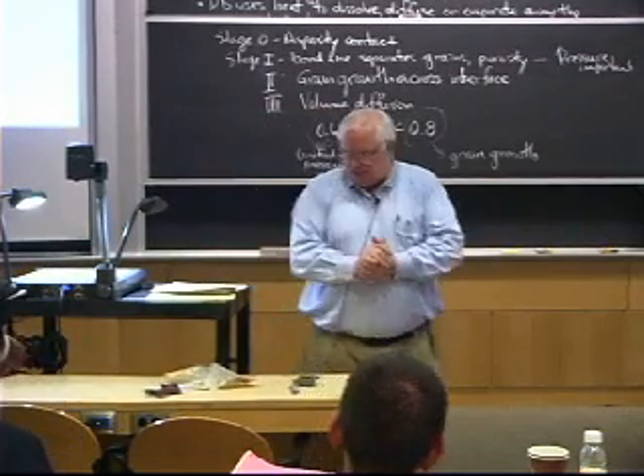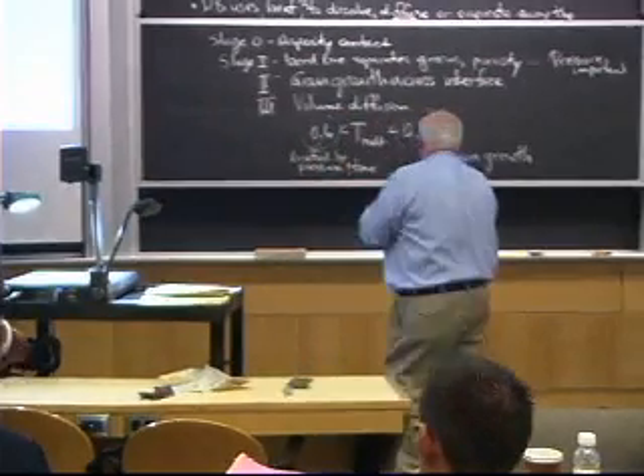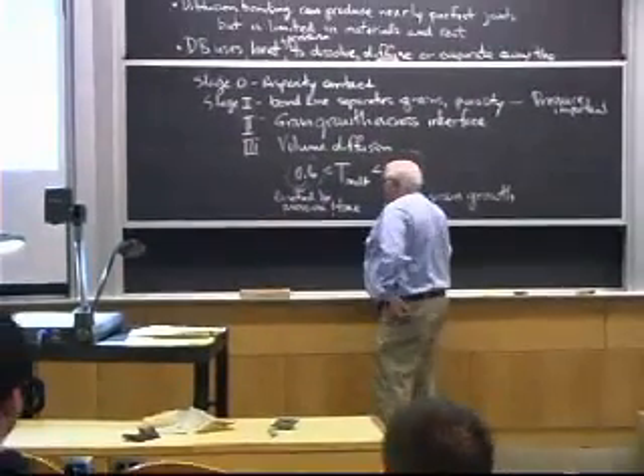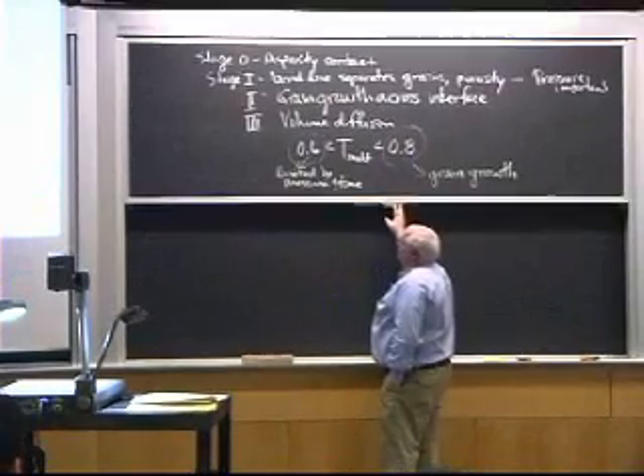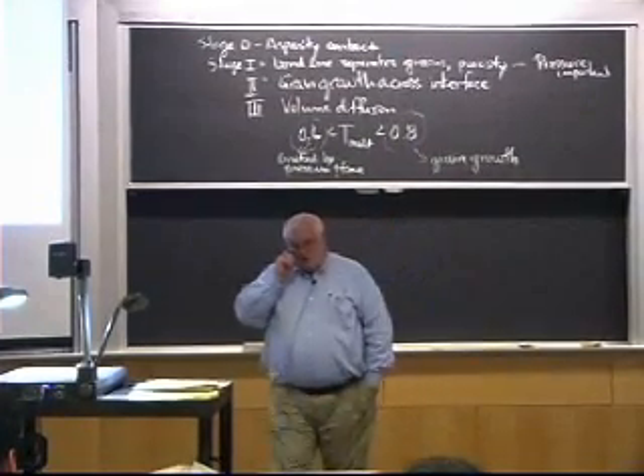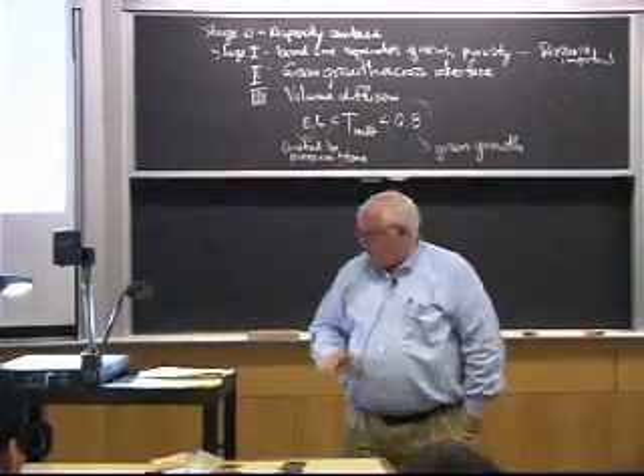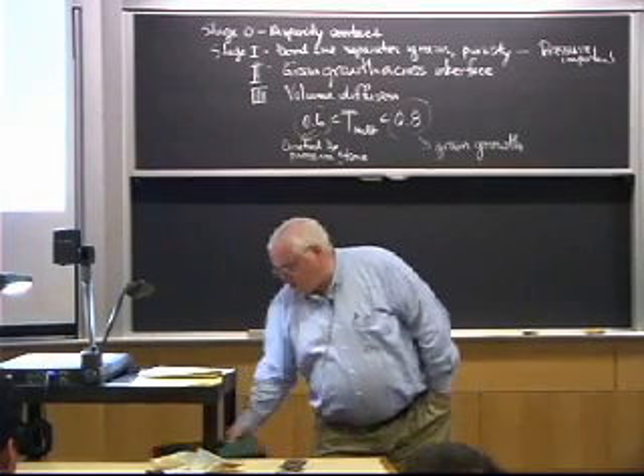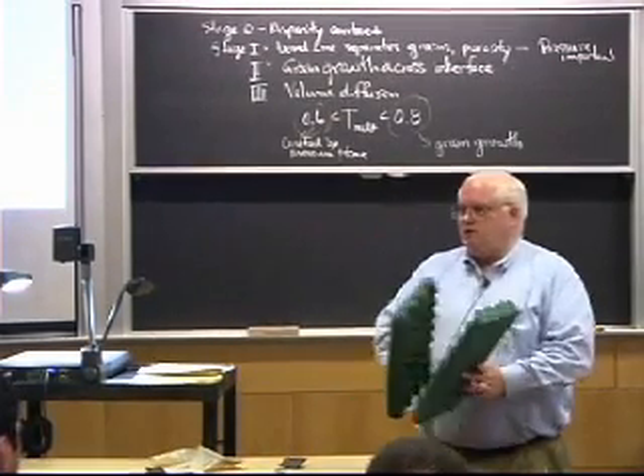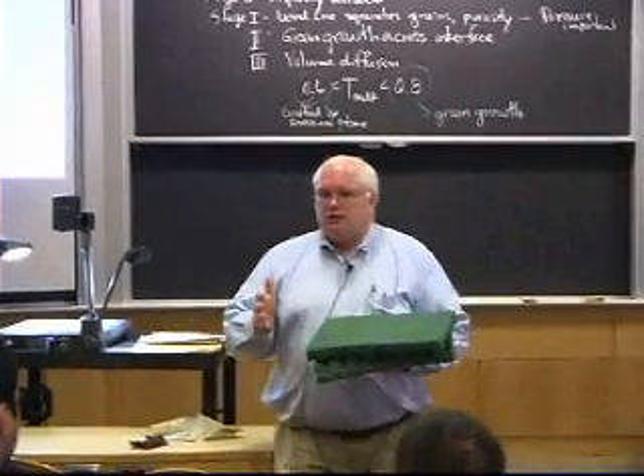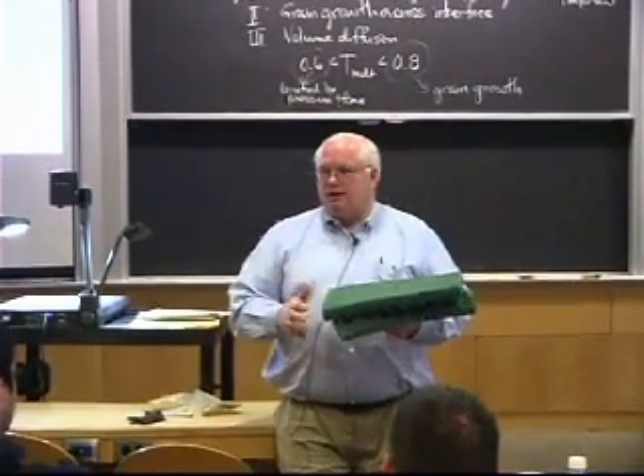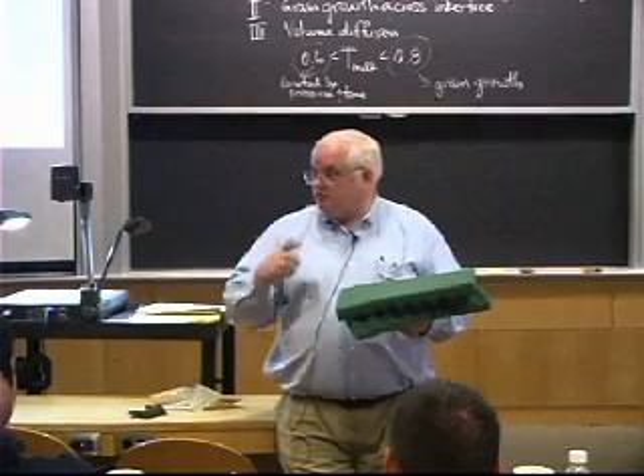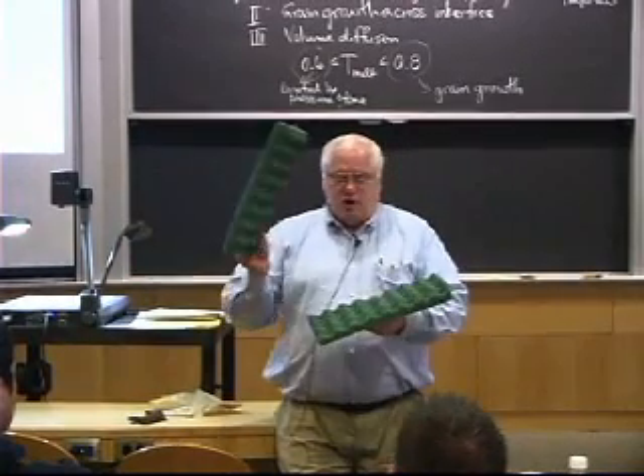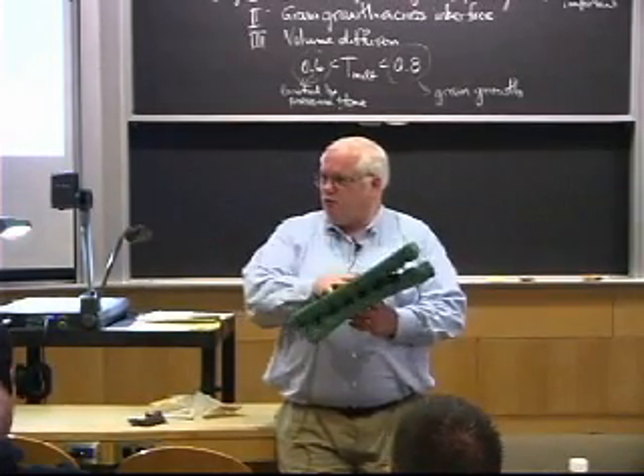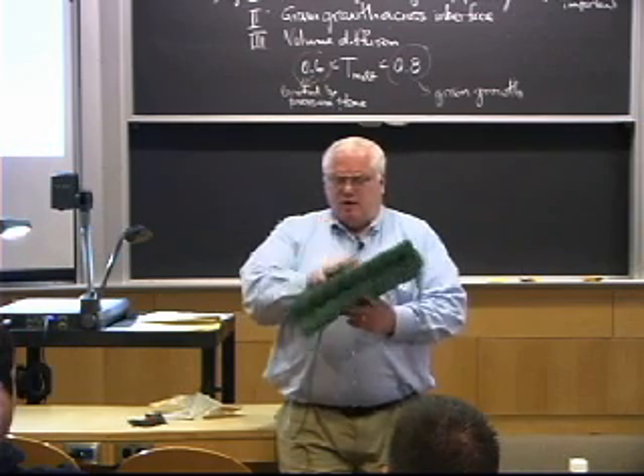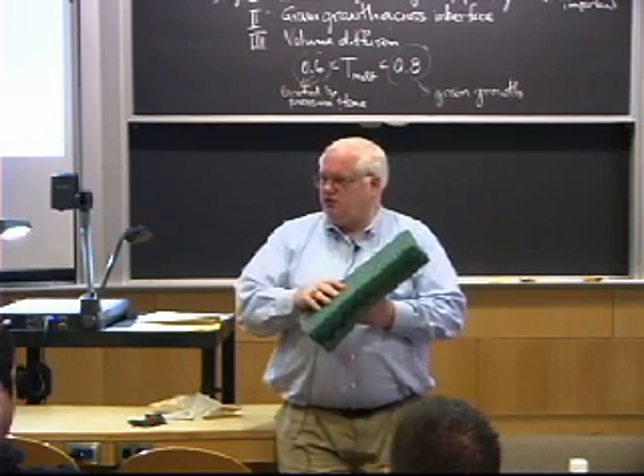So that's stories on superplastic forming, diffusion bonding, and whatnot. And you got all these complications for diffusion bonding. There is something that we use a lot more now that solves some of the problems that occur from straight solid state diffusion bonding, and it's called transient liquid phase diffusion bonding. Essentially it starts out as a braze and it ends up as a diffusion bond. And remember, diffusion bonding, I use pressure, I use heat, I dissolve away the oxides and stuff, and I use pressure to get the surface contact.